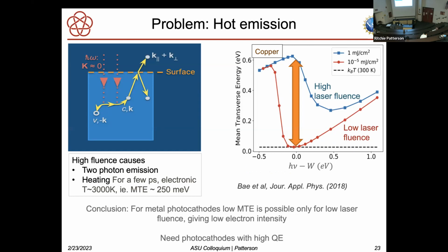At low laser fluence, you have very low mean transverse energy if you hit it with photons exactly at the work function, and then gradually the MTE increases as you increase the energy. Well, if you have a high laser fluence, then you have very high mean transverse energy, even when you hit it exactly at the work function. And in fact, that's been experimentally demonstrated also here at ASU by graduate student Chris Nill. So for metal photocathodes, low MTE and high current is not achievable.